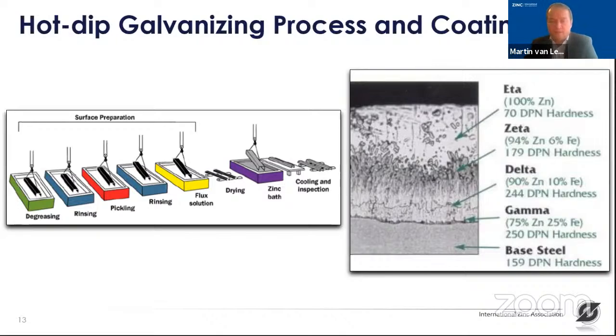The zinc will react with the steel: the iron will diffuse into the zinc, and the zinc will diffuse into the steel layer, and the final result is a galvanizing coating, which is a multi-metallic coating on top of the steel part. So the zinc coating has a metallic bond with the steel, therefore has a very high adhesion to the steel, and the intermetallic layers like the gamma and the delta layer can have even a higher hardness than the underlying steel itself. Therefore, these kinds of coatings are very abrasion resistant and very strong. You can smash a hammer on top of it without damaging the coating.